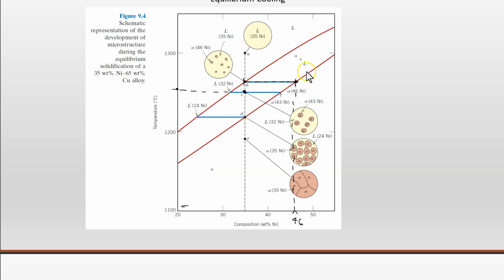So we know there's going to be two phases that are in equilibrium. How do we find out which phases are in equilibrium? We draw a horizontal line. We extend a horizontal line that is coincident with C. To the left, we keep extending it till we hit a phase boundary. To the right, we extend it till we hit a phase boundary. We now have our tie line.